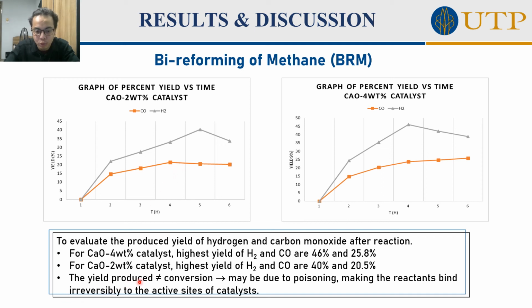So the yield produced is not equal to conversion, as I mentioned just now, which may be due to the poisoning of the catalyst, making the reactant bind irreversibly to the active site of the catalyst. And from this yield also, we can conclude that for both catalysts, we have achieved our expected syngas ratio of 2:1, which makes it successful and better compared to other catalysts.